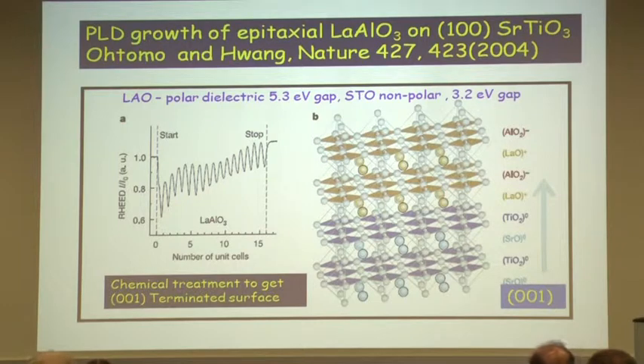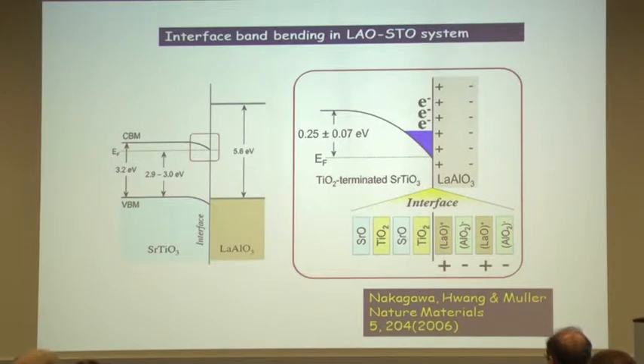And what they did, now, before I tell you what actually happened, consider lanthanum aluminate, it is a polar dielectric with a band gap of about 5.3 electron volt. And strontium titanate is 3.2 electron volt. Both are highly insulating materials. But it turns out that if you deposit something like 5 to 6 unit cells of lanthanum aluminate on top of this, the interface actually becomes highly conducting. And you actually have a two-dimensional electron gas at the interface.